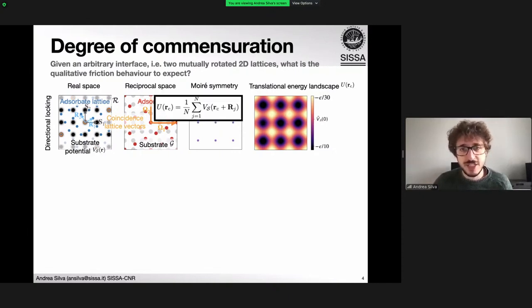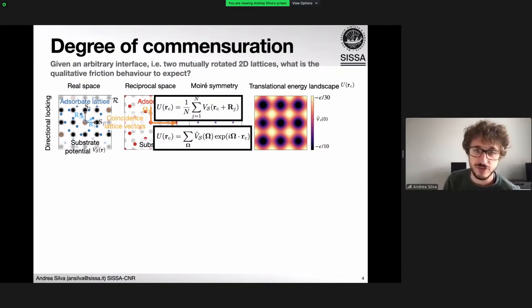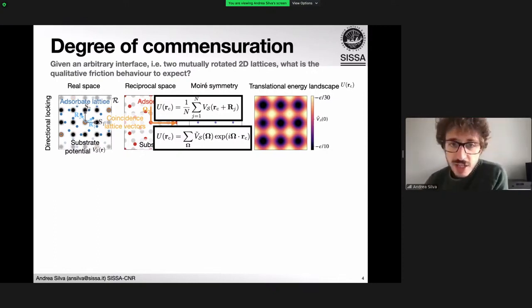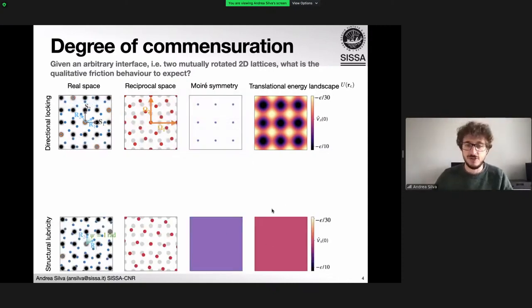And just to get a bit more detail, this can be computed numerically, which is usually done in codes by really summing over the atoms building up the interface, or we did it by using a Fourier transform of the potential, which is an exact match in this periodic infinite system. So this is the case of directional locking, where friction is high and you expect stick-slip. On the other hand, we would have structural lubricity, where the system can slide freely in any direction. So the energy landscape that we see here is flat. This means that the two lattices are incommensurate, but mathematically there could still be a coincidence lattice vector in real space, but if there are none in the reciprocal one, then you would expect to see this sort of flat energy landscape.